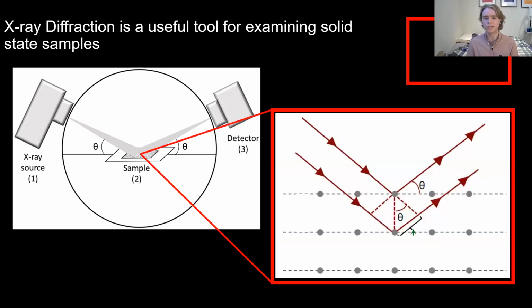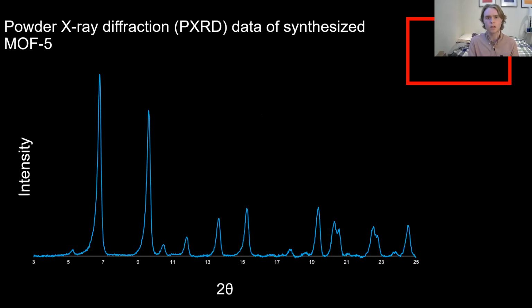Now, on a microscopic level, what we're really looking at here is a lattice of our atoms. So if we imagine that these gray dots are atoms set up in this lattice construction, and the red incoming arrows are our X-rays, what we're going to see is that we're looking at deflection off of various sublevels of our framework. So we see that some X-rays will bounce off of the top level, bouncing off of a gray dot. Some will be able to penetrate a little deeper and bounce off of a different atom. And actually, depending on how you measure the path length difference of the X-rays after they've been reflected into the detector, we're actually able to get measurements out for different distances between different atoms in the framework.